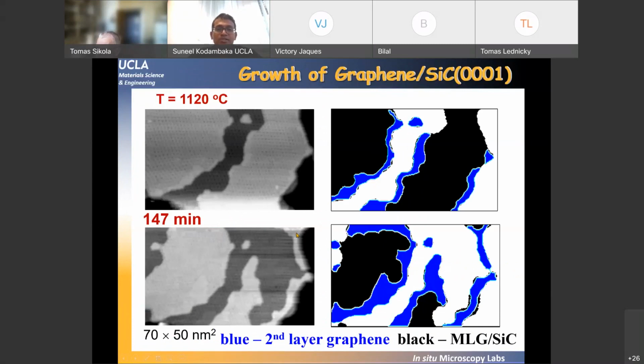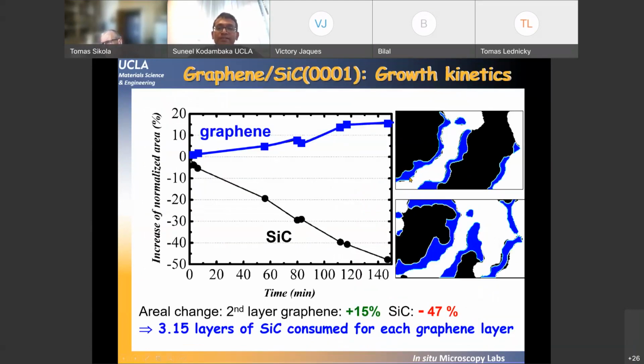And these are the snapshots, and this is for your benefit. I've color-coded the regions so that you can see the bilayer graphene, and the bilayer graphene coverage increases after 147 minutes, indicating that you have more graphene growth, and we can quantify this process. When you plot the areal coverage of a given layer as a function of time, you see that the graphene coverage increases and the silicon carbide coverage decreases, and the amount of change in silicon carbide is roughly 3 times that of the increase in graphene coverage. And that's what you would expect, that you need 3.15 layers of silicon carbide to form 1 layer of graphene.